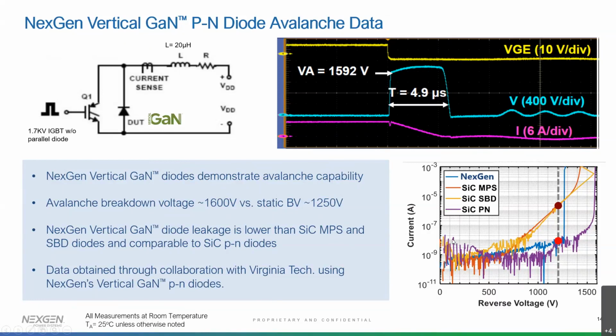And in the lower right-hand picture, you see how our device, which is the dark purple one here, behaves in comparison to different silicon carbide technologies. And you see that we are breaking down at 1600 volts, as described in the oscilloscope picture. But you see also that our leakage current is much lower than many of the silicon carbide devices here. They rise in leakage current until the point where the avalanche actually happens. But the vertical GaN diode leakage current stays relatively low until the breakdown